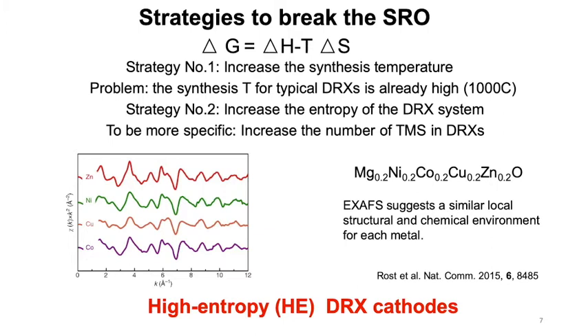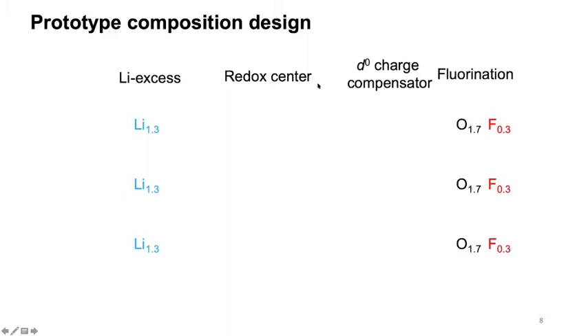So that comes to our strategy of designing new high entropy DRX cathodes. When it comes to the composition design of DRX material, we usually need to consider 4 different aspects: lithium excess level, redox active center, D0 charge compensator, as well as fluorination level. And in this study, I use lithium 1.3 as the lithium excess because it will guarantee enough percolating lithium, while on the other hand, not put too much limitation on the transition metal redox capacity. And we also use fluorine 0.3, that is 15% fluorine substitution, in order to increase the amount of transition metal redox.